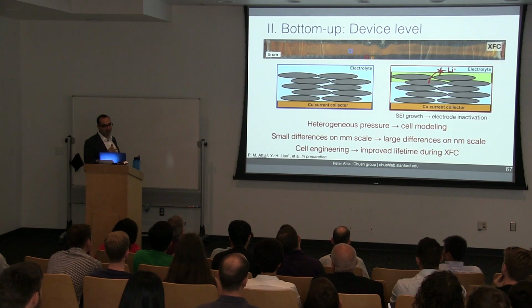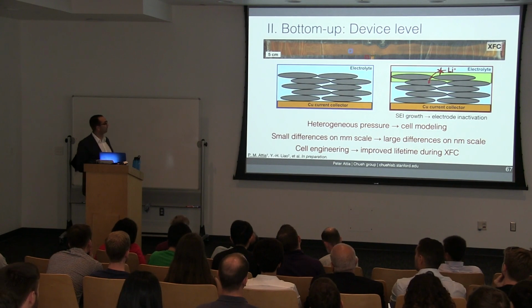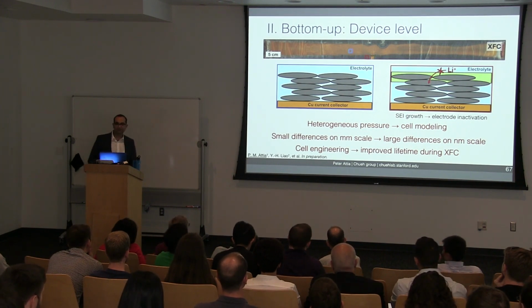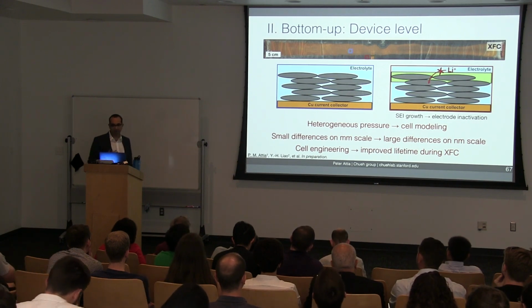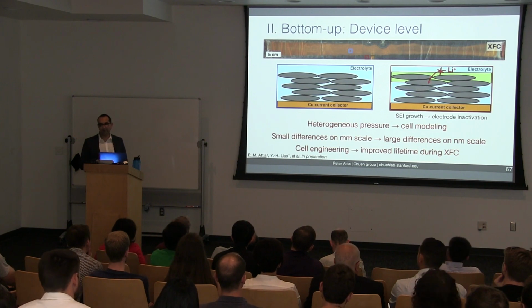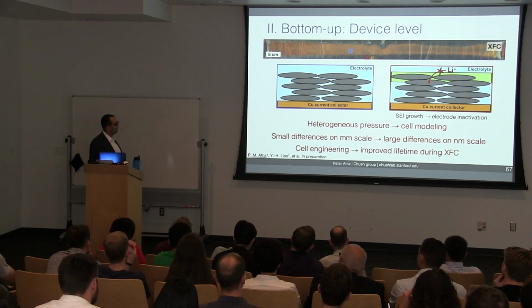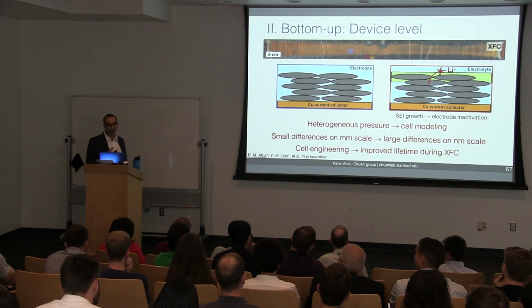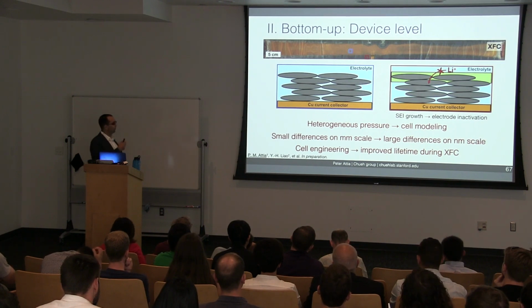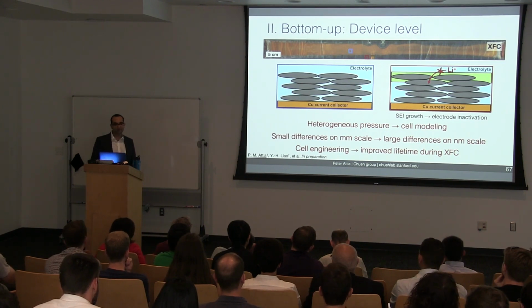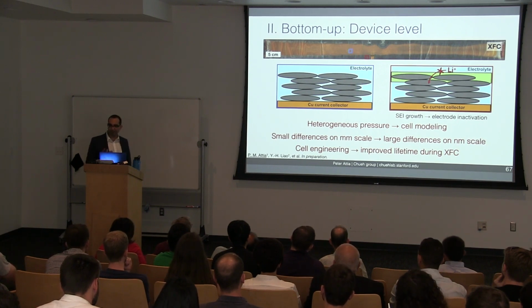On the device level, we saw how fast charging led to widespread electrode inactivation, which was caused by the presence of a large SEI layer on the surface. We had 3 conclusions. First, we saw the importance of pressure in degradation. Since pressure often is not incorporated into battery modeling, understanding the effect of pressure needs to be the focus of future battery model work. We also saw how complex battery degradation can be. Small differences in stack thickness on the cell level can lead to really massive differences on the pack level. This really motivates the need for device level studies, since the dominant failure modes may not occur in small scale testing. And lastly, we considered how device level optimization efforts, like tab engineering, could lead to dramatic improvements in lifetime during fast charging.